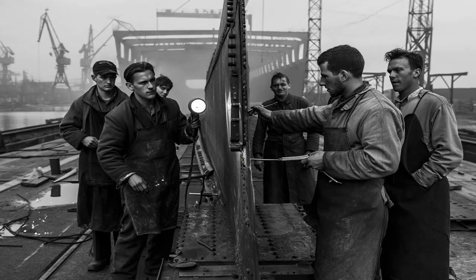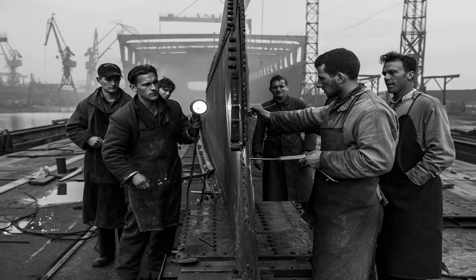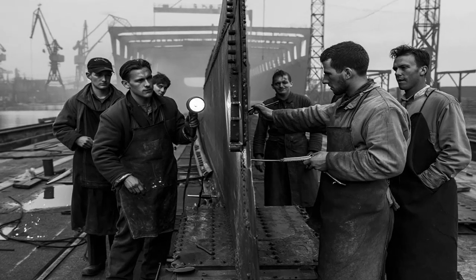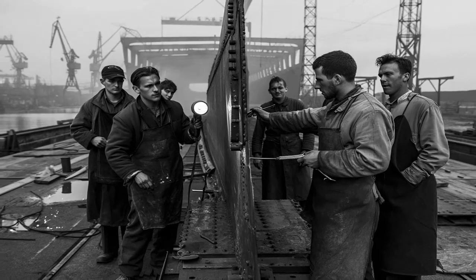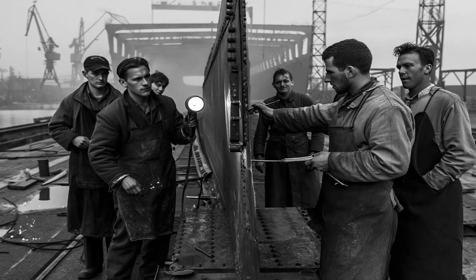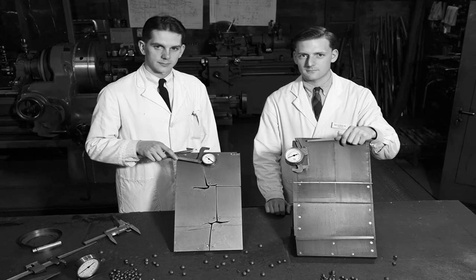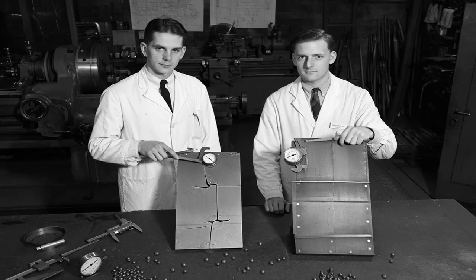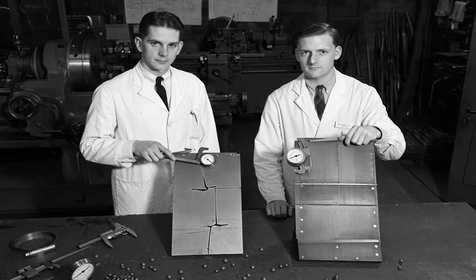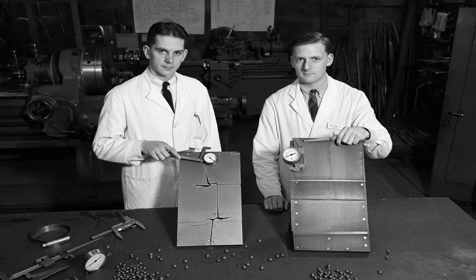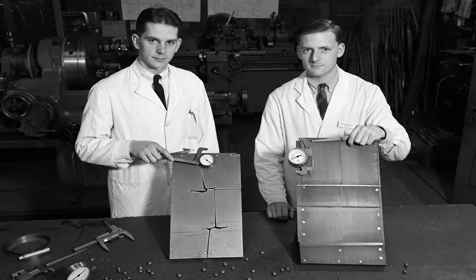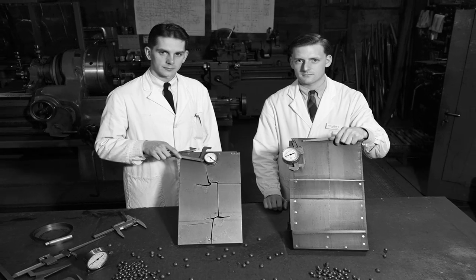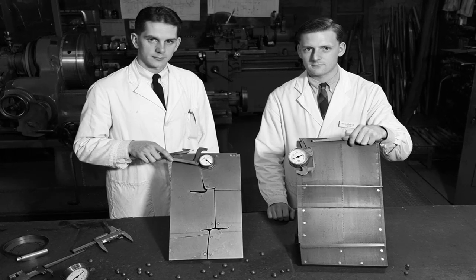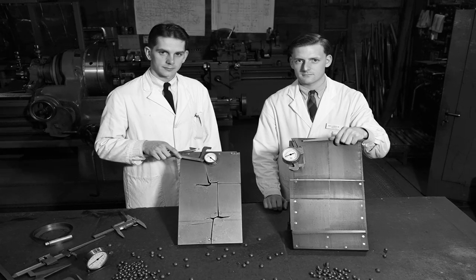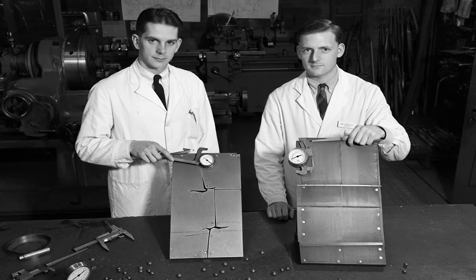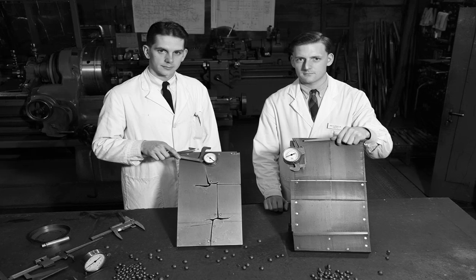He greenlit prompt trials of Hamill's concepts, halting a full base segment mid-production for a trial rebuild. Experts in metallurgy and design, who had devoted months dissecting wrecked vessels, now deferred to an evening shift fabricator without any formal academic background. The outcomes were both condemning and transformative. As Kaiser's specialists scrutinized panels made via standard procedures against those following Hamill's strategy, the contrast was quantifiable and striking. Instruments measuring lingering strains revealed that conventional joints held pressures over 30,000 pounds per square inch, focused at critical junctures. Hamill's ordered panels spread those forces over wider zones, with maximum levels just topping 12,000 psi.